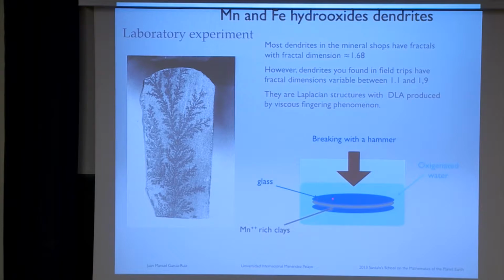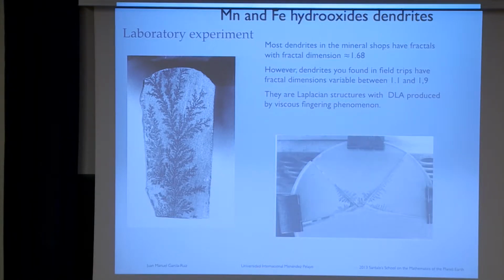Well, we made this experiment. We have the two glasses here, and then we use toothpaste, because some toothpastes have quartz nanocrystals, okay? So the toothpaste here with some manganese 2 and iron 2 solution in the toothpaste, okay? We put it in a reservoir, and we fill the reservoir with oxygenated water, okay? What we did is just, with a hammer, you crack the glass, and when you crack the glass, you provoke that the air penetrates and immediately oxygenates the toothpaste, and then what happens is that you really form the fractal dendrite.